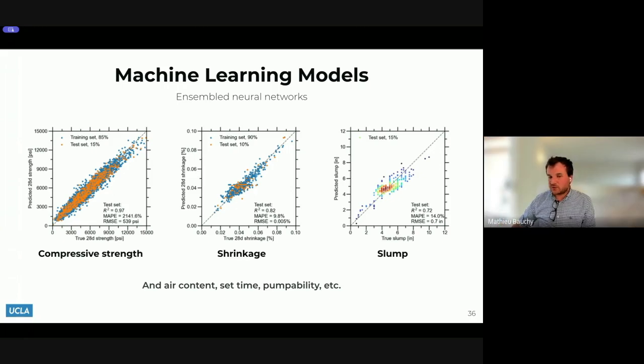So we typically have two layers. When we do this leave-one-cluster-out, we first take our data set and group it into clusters, then we isolate certain clusters, and that's what we use as the final test set. Then we use the rest to do the cross-validation, right? So what I'm showing here is the test set accuracy of predicting those clusters that were isolated from the very beginning. So it's like a traditional test set, but really in the context of extrapolating to new clusters.